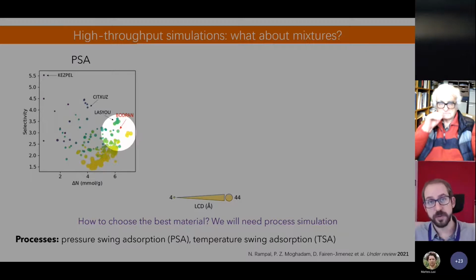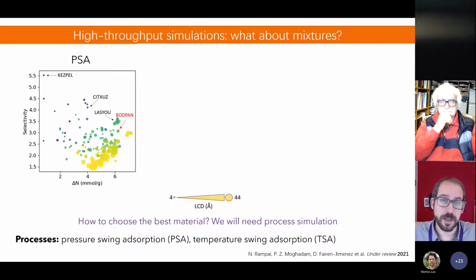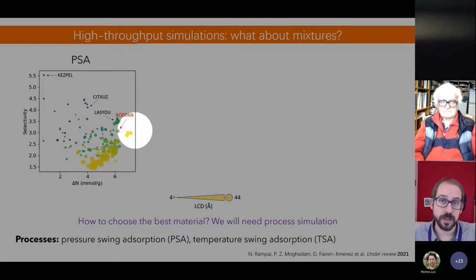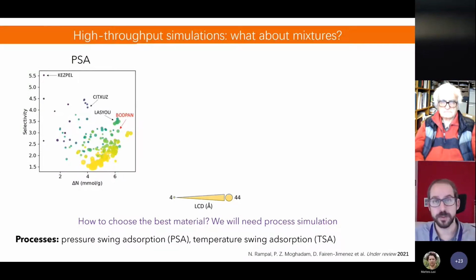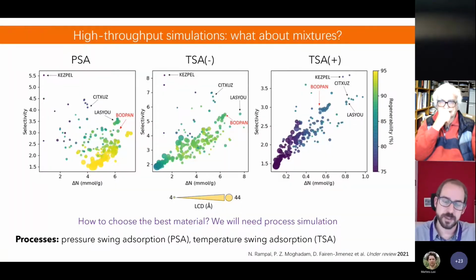And if a material has a high working capacity, it means it stores a lot of CO, it removes a lot of CO, but also the selectivity cannot be very, very high because this material is not going to be having those specific interactions. So this is a kind of multivariable game where we really need to take into account all the different possibilities to define what is the best material. And this is something we really need to build. This is something we really need to understand. We have then a transformation into the temperature swing adsorption process. From the PSA, we move to the TSA, decreasing the temperature or increasing the temperature, and we can really have all these different values. But the key question here is that to choose the best material, the optimal material, we really need to use process simulations.